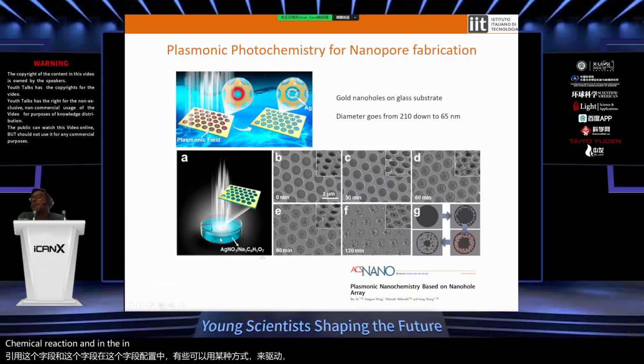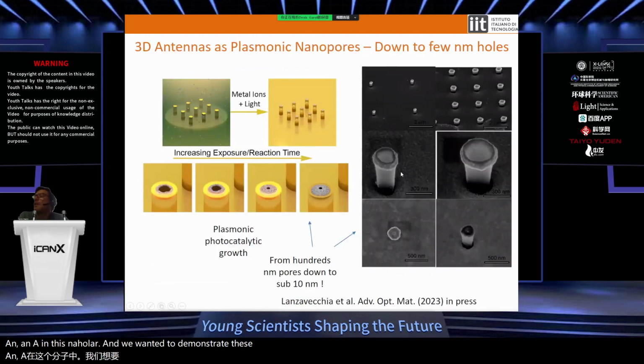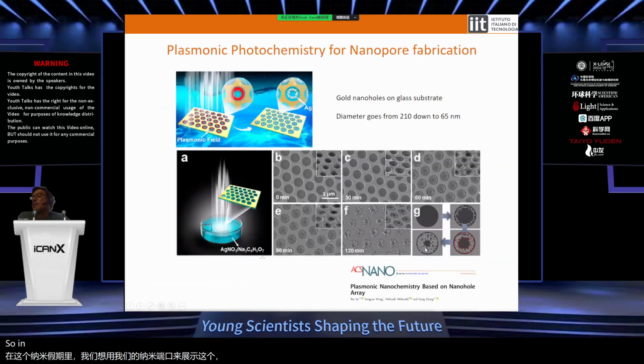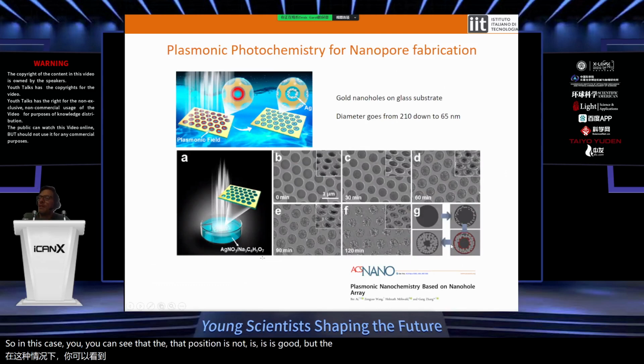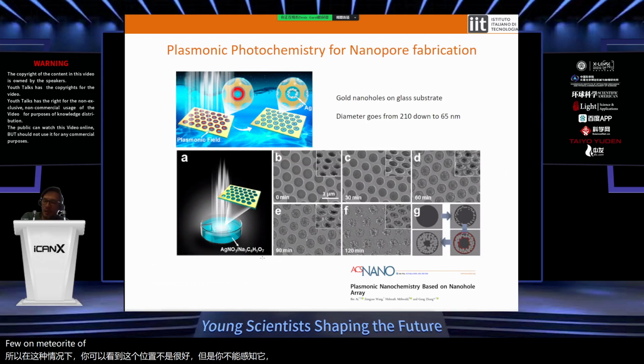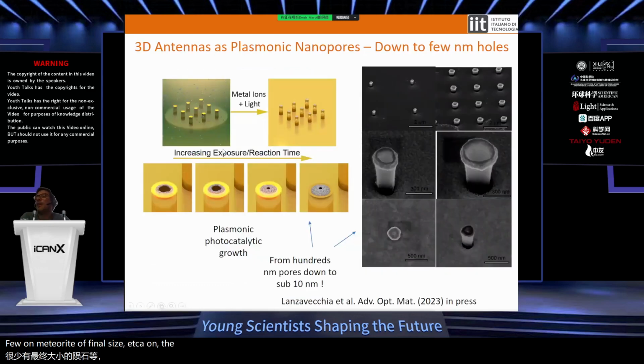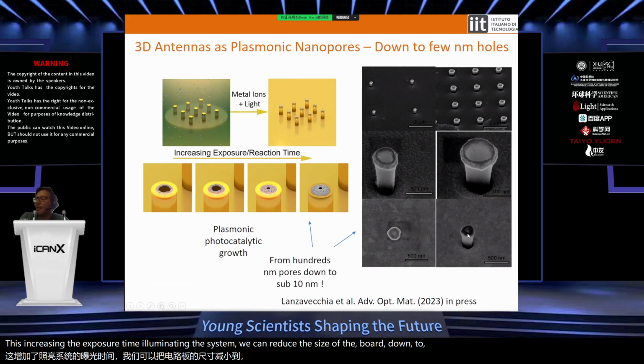And in particular, in this paper, it has been demonstrated that the electromagnetic field confinement can drive the reduction of a silver salt in this nano-hole array. And we wanted to demonstrate this in our nanopore. So in this case, you can see that the position is good, but you cannot achieve a few nanometer of final size, etc. On the contrary, here we used our 3D design in order to go from increasing the exposure time, illuminating the system. We can reduce the size of the pore down to, according to our measurement, less than 5 nanometer.